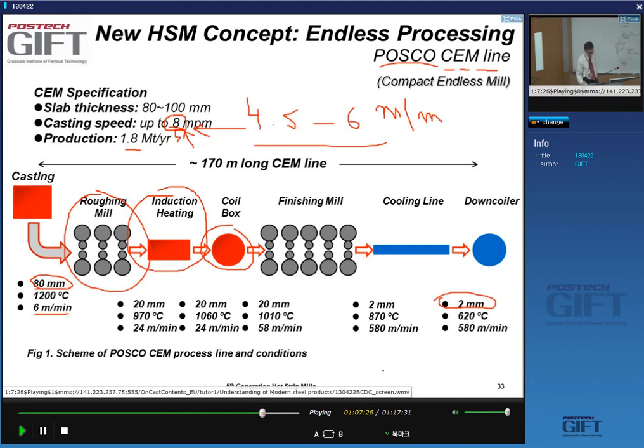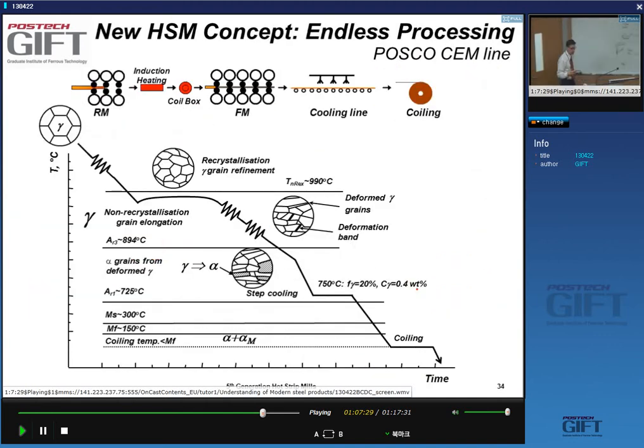Right, so this is schematically the production line. So similarly to the situation that you have in a hot strip mill, you can look at what happens in such a line. So you start off with a relatively coarse gamma grain. The roughing mill that you use now will allow you to get a grain refinement, yes? The heat you lost during the roughing, you gain back during the induction heating. In the coil box, the temperature is equalized and there's very little loss.